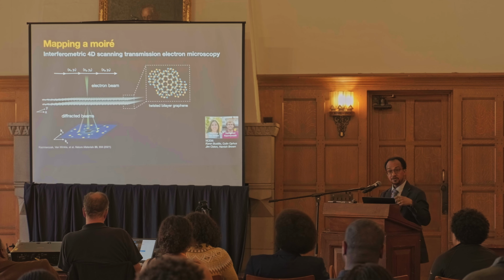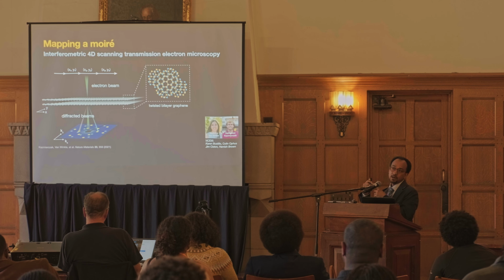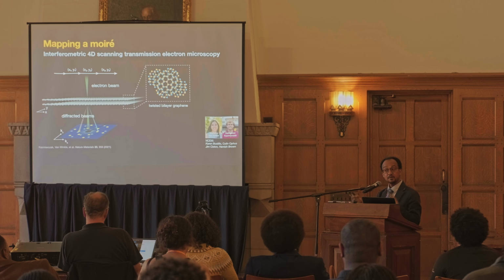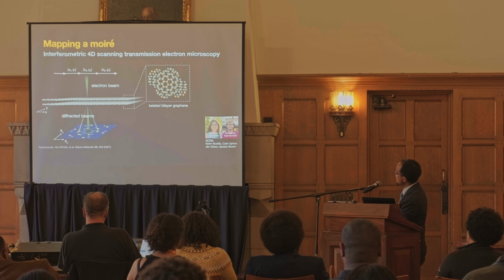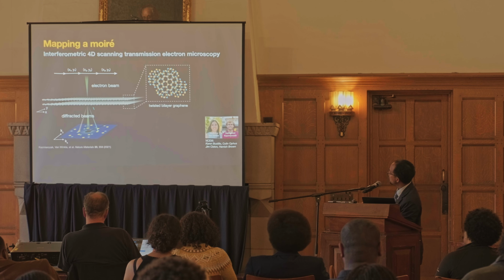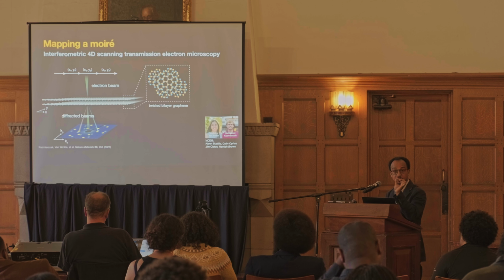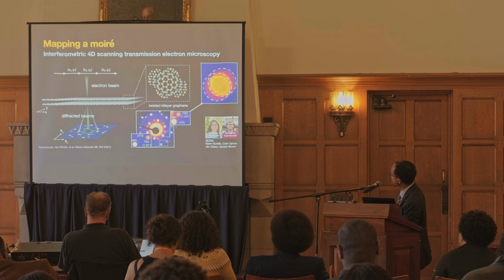We have an electron beam that we focus, and we pass it through the material. Traditionally, in electron microscopy or in any microscopy experiment, you ask, for this beam that is going through my material, how much of it is absorbed and how much of it goes through? What we did instead is a sort of dark field experiment, where we're asking how much of that beam is scattered? Specifically, how much of it is diffracted? And then we take those diffracted beams from each layer. Each layer will nudge the beam a little bit, and that's going to give rise to a diffraction pattern.